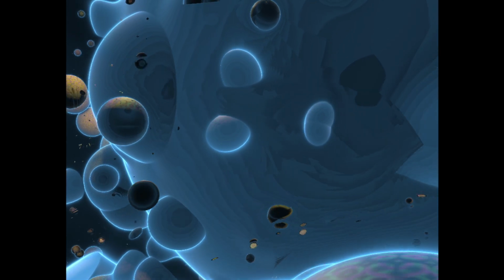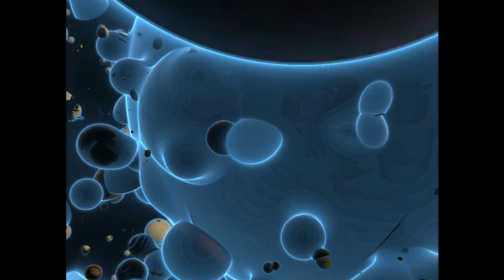Several things. One key piece is the observation of a neutron spin resonance. This is a collective magnetic excitation that appears only below the superconducting transition temperature, Tc, at that same wave vector. Why is that significant? Its energy and momentum dependence are exactly what you'd expect if the superconducting gap changes sign between the pockets connected by that vector. It's like a fingerprint of this s± state. Okay, any other evidence? Phase-sensitive measurements, often using STM, scanning tunneling microscopy, looking at how quasi-particles interfere, have also provided strong, though sometimes debated, evidence for this sign reversal between pockets in many FeSCs.